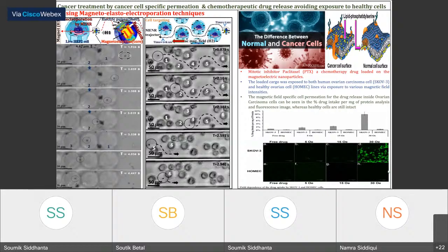So this proves that at this magnitude, at this particular magnetic field, we can have a targeted form of treatment of these ovarian cancer cells by releasing the chemotherapeutic drug to those targeted areas only, rather than the chemotherapy technique where the whole body is exposed, because they were not able to distinguish between or particularly target the cancer cells rather than the healthy cells, and they kill all of that, which has a very high side effect.